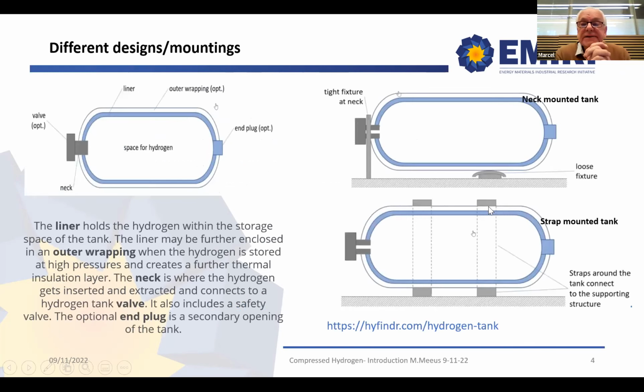What are the different designs and mountings for compressed tank storage? On the left-hand side, you see the space of hydrogen that will be filled, and the liner around that space, in fact, is decreasing or blocking the permeability of the hydrogen, and that liner can further be enclosed by an outer wrapping for high pressures, and that outer wrapping serves as load bearing and as insulation layer.